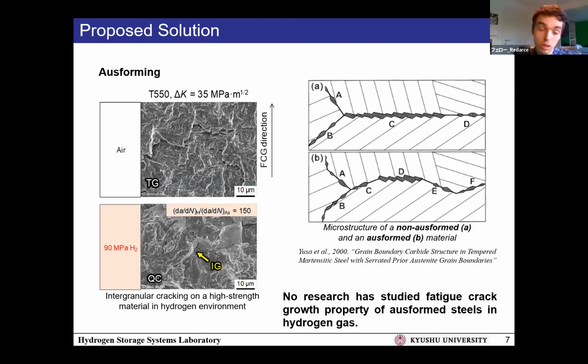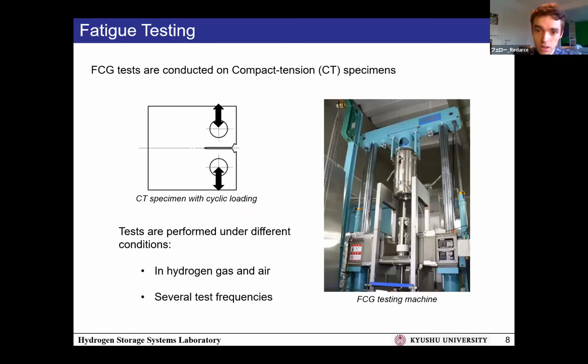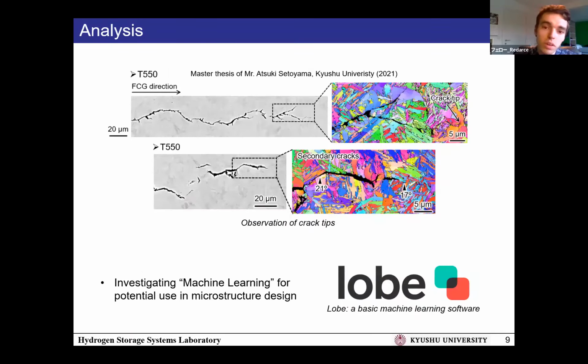A lot of research has been made on hydrogen embrittlement. Some research has been made on ausformed materials, but there is currently no other research that combines both ausformed materials and hydrogen embrittlement. So we'll do that by doing classic compact tension specimens to test the fatigue crack growth in many different ways: in hydrogen gas, in air, at different hydrogen gas pressures, and of course different test frequencies. Then there will be observation of the crack propagation path and crack tips, to try to determine and analyze the propagation of these cracks.